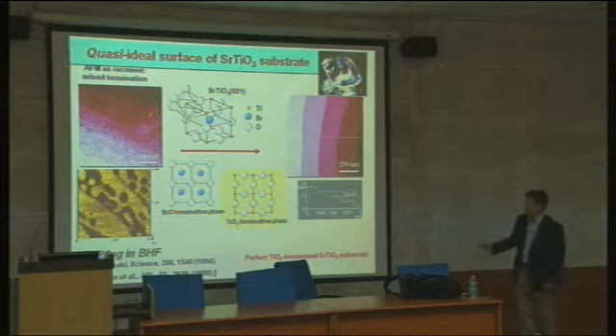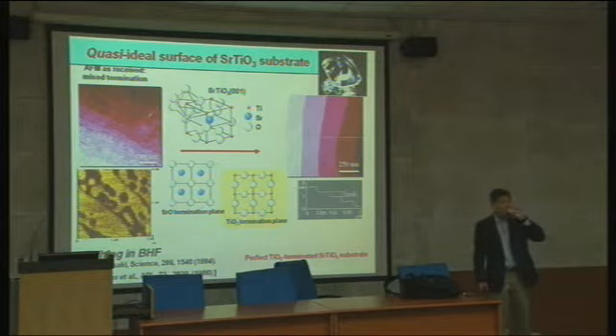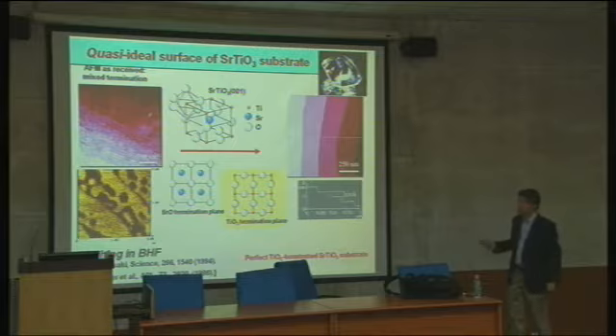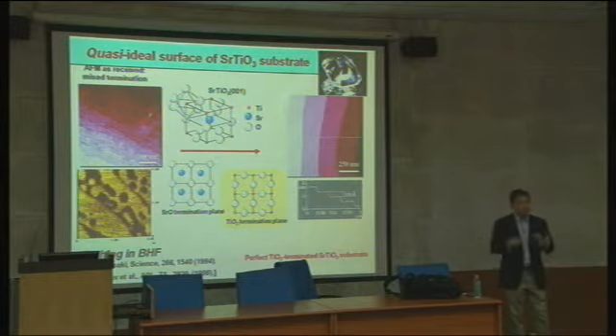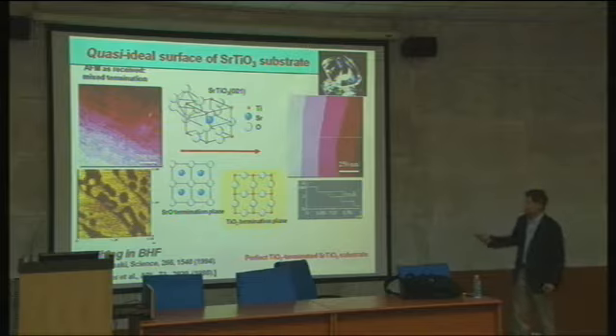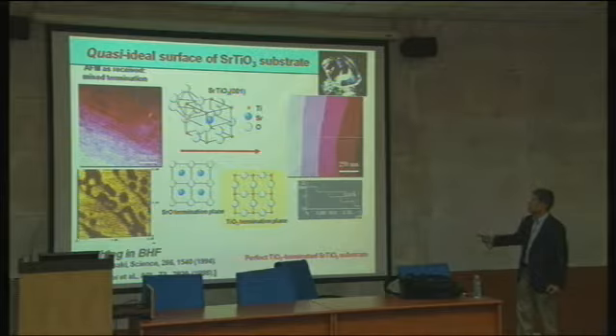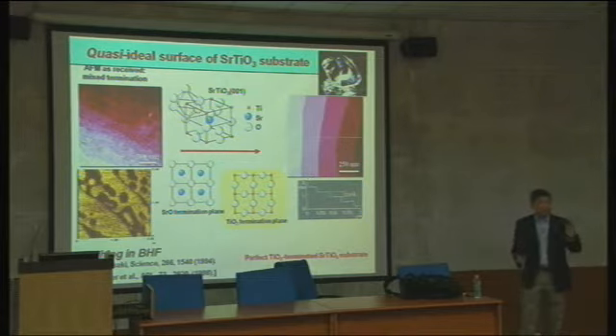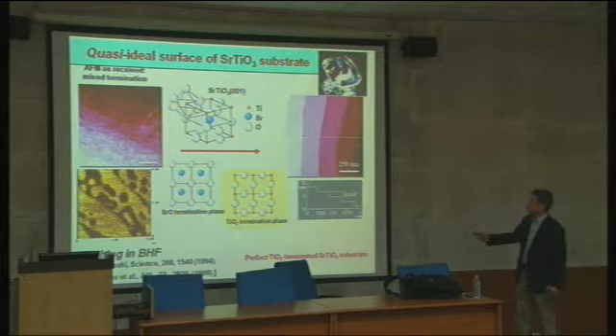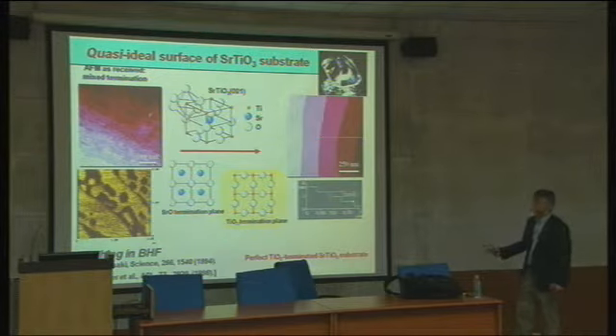And then you can actually see it, if you look at this atomic force microscope image. Has anybody done AFM imaging here? You need AFM imaging. And this is the step height, your section analysis. This is a typical step structure you can make in thin films. You can see here, step 1 and going up, up, up. Each step is 4 angstrom, which is the same as this height. Okay? This is the full unit cell height, because the titanium layer and the next titanium oxide layer are roughly 4 angstrom apart, exactly 3.905 angstrom, but roughly 4 angstrom. And each step is roughly 4 angstrom.